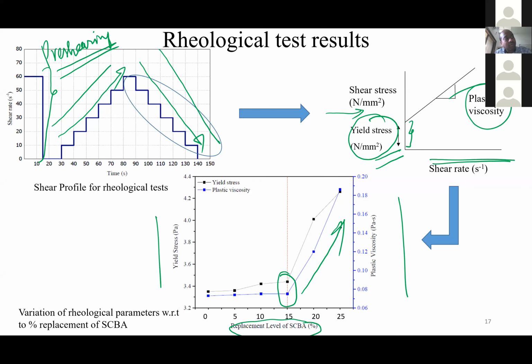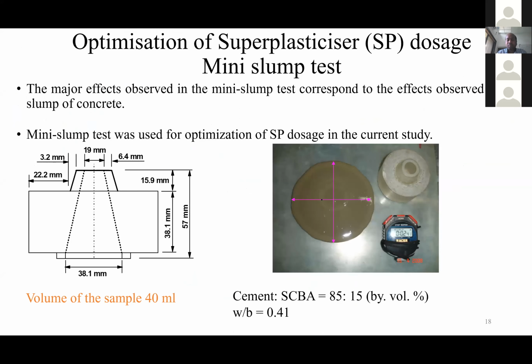What kind of issue will it have? These issues will be there in terms of resistance for flow and other things. So it is very evident that the 15% which gave maximum packing density is getting reflected here. Up to that, there is not much of a difference in values, both viscosity and yield stress. But beyond that, the values are increasing tremendously, which clearly states that 15% is optimum for this particular combination. So we have optimized the